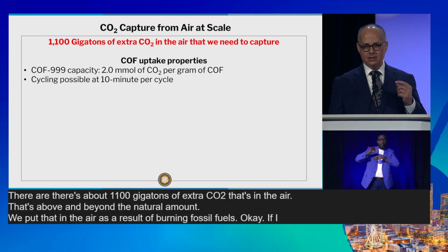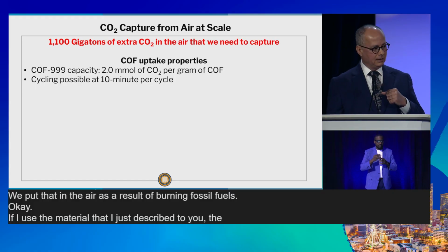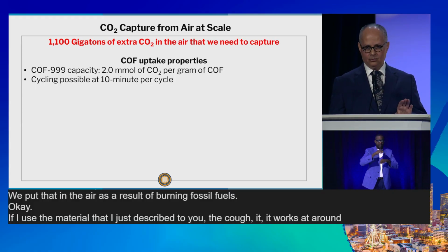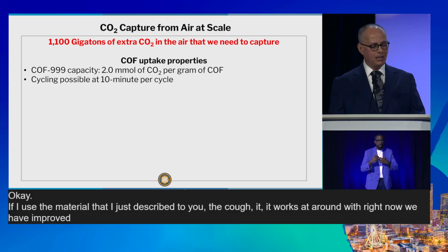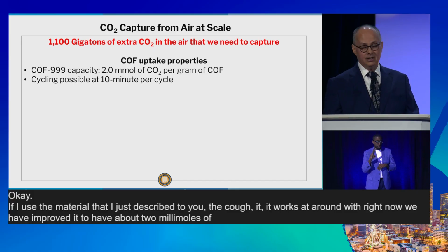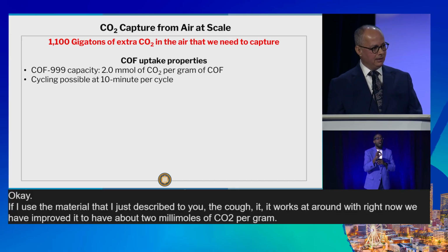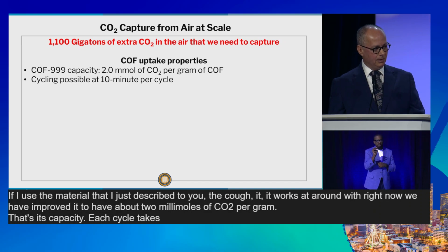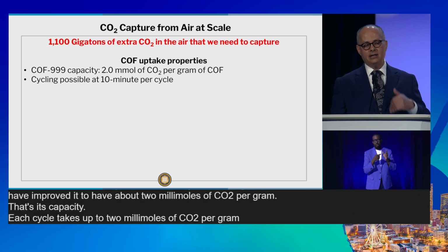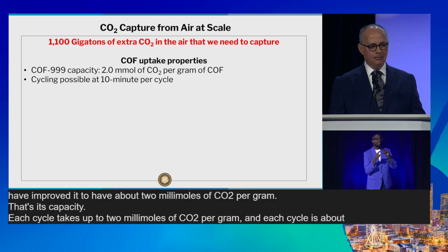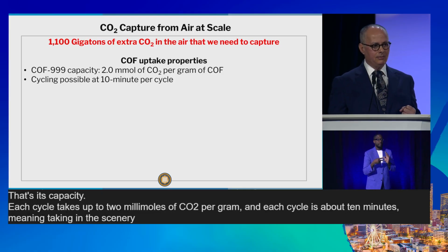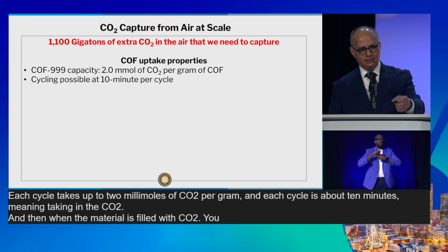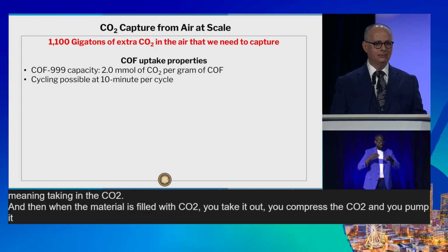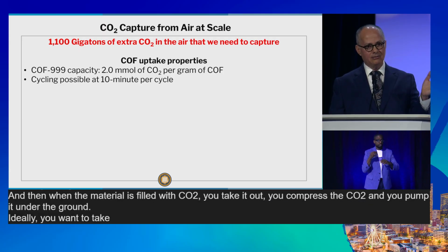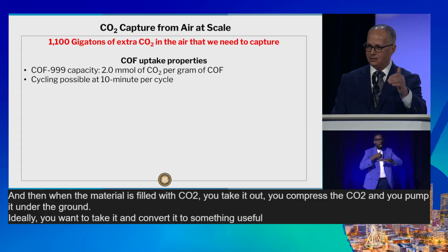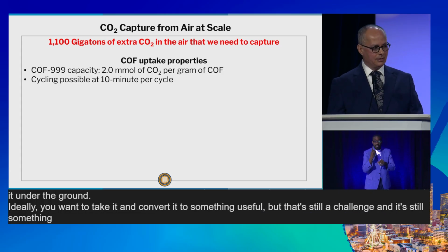Okay, if I use the material that I just described to you, the COF, right now we have improved it to have about 2 millimole of CO2 per gram. That's its capacity. Each cycle takes up 2 millimole of CO2 per gram. And each cycle is about 10 minutes, meaning taking in the CO2, and then when the material is filled with CO2, you take it out, you compress the CO2, and you pump it under the ground. Ideally, you want to take it and convert it to something useful. But that's still a challenge, and it's still something that we are researching.